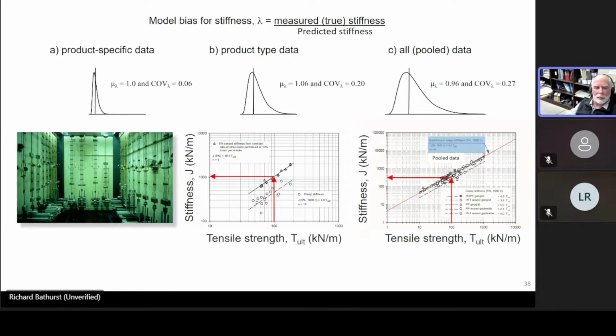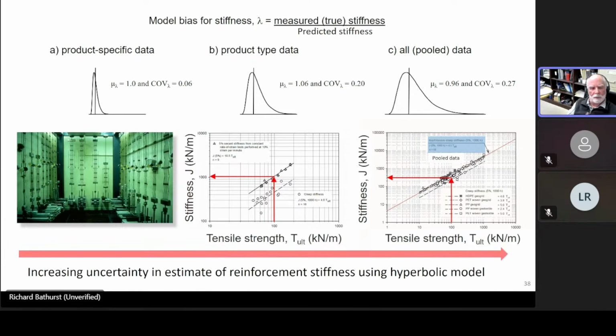However, the slide shows that there's increasing uncertainty in the estimate of the reinforcement stiffness using this hyperbolic model as you go from product-specific testing to product type data testing to pooled data testing. So there's an argument that says use product-specific data if you have it, because that'll increase your confidence in the estimate of the nominal factor of safety for each one of the limit states that we talked about.